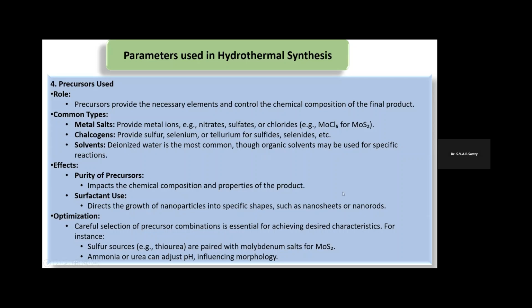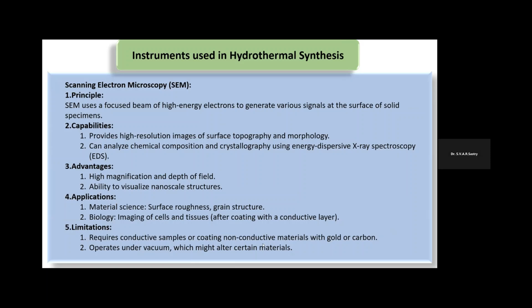As we discussed before, there are different types of nanoparticles: zero-dimensional, one-dimensional, two-dimensional. For the application of nano lubricants, we prefer using two-dimensional nanoparticles. To have two-dimensional nanoparticle morphology in the autoclave, we require the use of surfactant. So again, optimization is a key factor. For example, a sulfur source like thiourea can be paired with a molybdenum salt for making MoS2 nanoparticles. Similarly, we can also use ammonia or urea to adjust the pH, and pH can also influence the morphology of the final formed nanoparticles. So these were the 4 different parameters which can control the reaction in the autoclave.